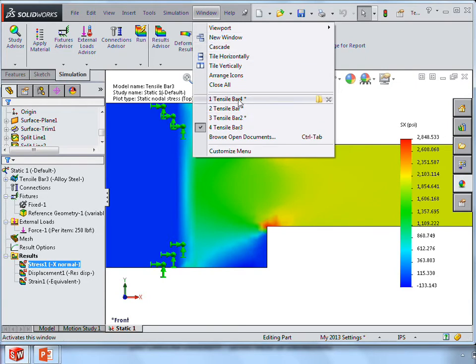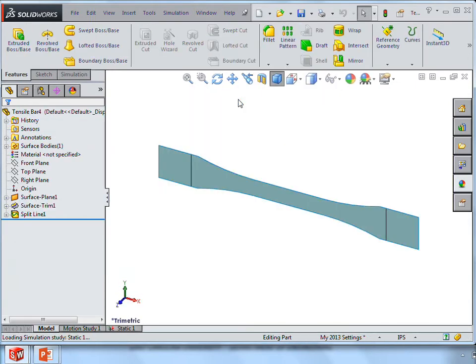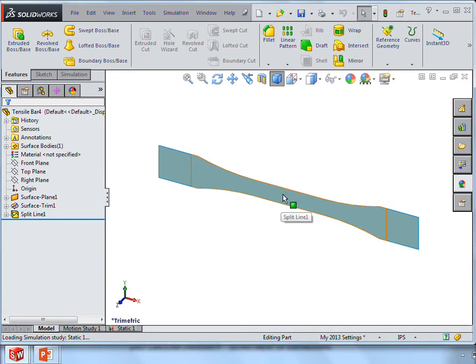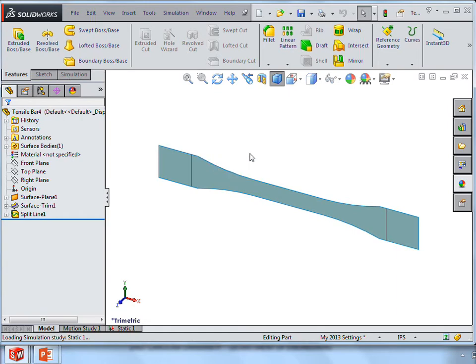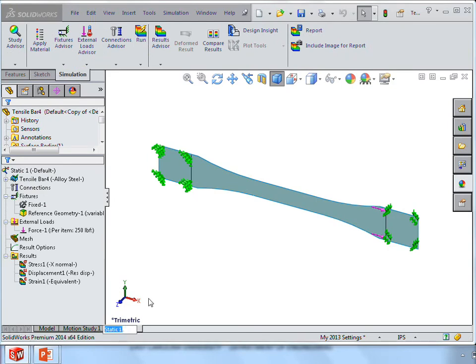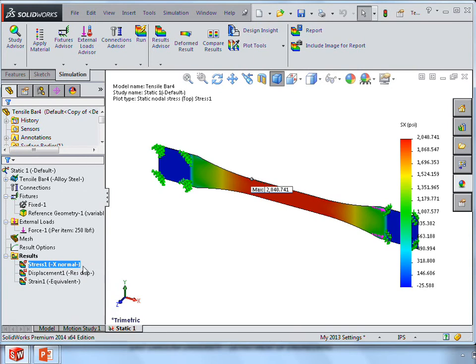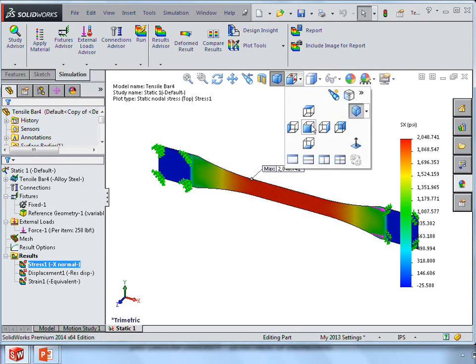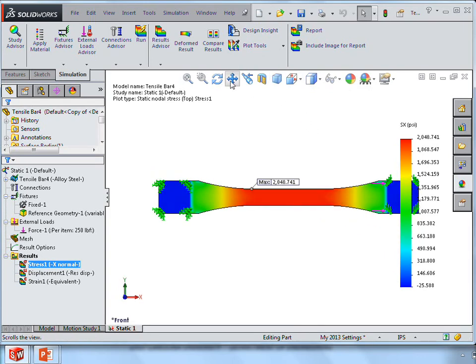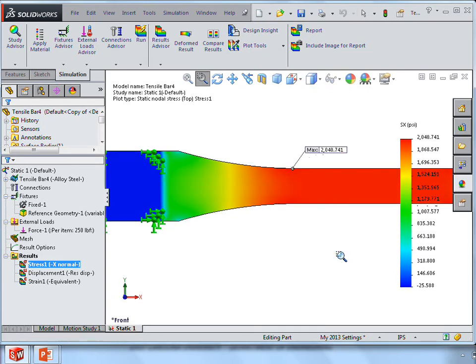So what we'll often do, and what's written into a lot of codes, ASTM testing codes, is the geometry of what's known as a dog bone. And so the dog bone still does thin this out, because you want to try to force the failure out into the center. But it does that without any sharp corners here, and with a very nice gentle radius in these regions. So if I show the stresses for this one, you can see we still get a little bit greater than 2,000 psi, but not much. Only about 2%. It's impossible to get rid of that stress concentration completely, but certainly we've smoothed it out to within a couple of percent.